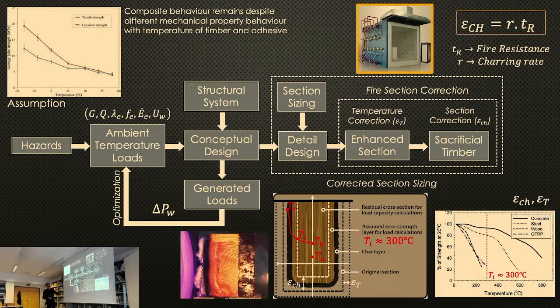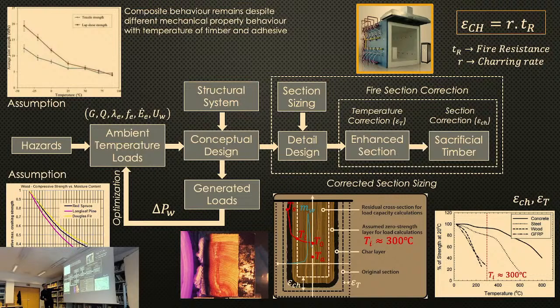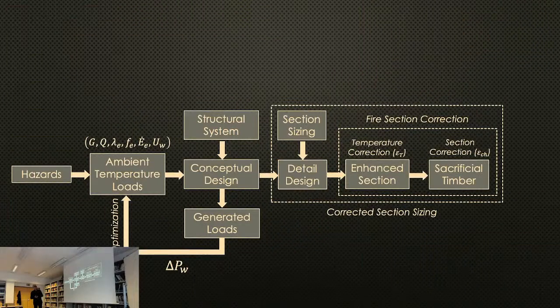Now, another problem is moisture migration, because water is going to migrate through the porous media, and we know that then it's going to accumulate and you're going to have very high moisture levels. Now, the problem is that the decrease in mechanical properties with moisture is extraordinarily fast. So as soon as you start increasing the moisture content, your mechanical properties go down to zero. And as a result, you get concentrations of stresses and you get the material cracking. So the material splits because there's no mechanical strength here and there's more mechanical strength here, and therefore at the char layer, between the two of them, you're going to find your cracks. So none of these things are incorporated. They're all somehow ignored.